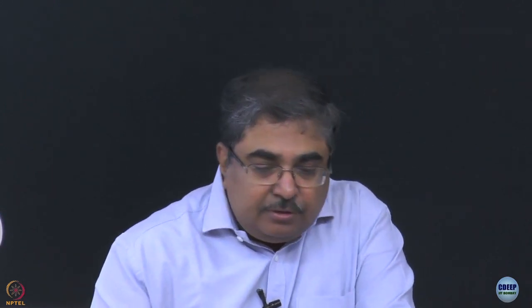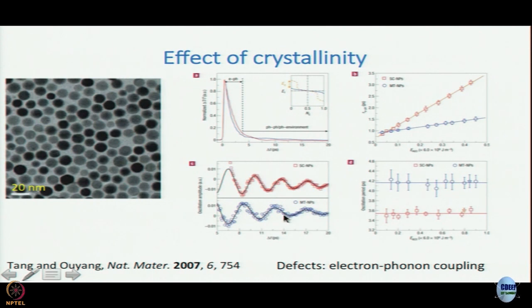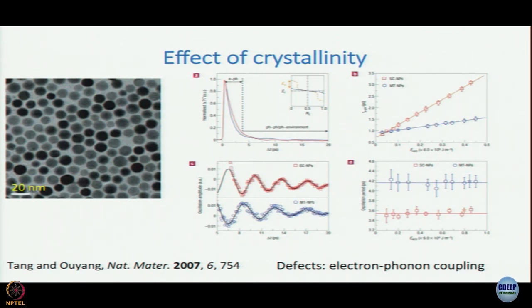The frequencies remain the same irrespective of the pump power absorbed. The oscillation frequency is lower for the single crystals than for the non-crystalline forms, which also tells you that coupling is weaker. This oscillation is also a consequence of electron-phonon coupling, so the coupling between electrons and phonons is weaker when you have better quality crystals.